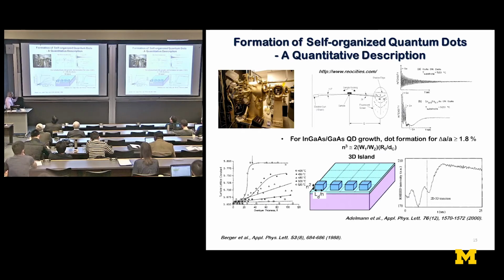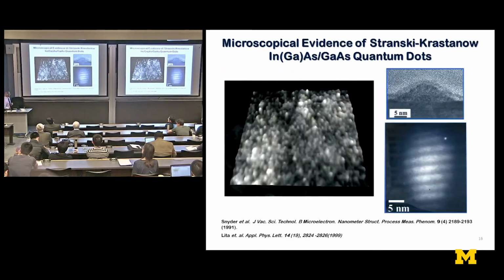And with that, we predicted that for a mismatch greater than 1.8%, and it's now known as the 1.8% or 2% rule, you will have the formation of islands. And we were glad to see after many, many years when people started working on nitride semiconductors, that the 2% rule was borne out here also. When you grow indium gallium nitride on gallium nitride for 18% indium or higher, you get this 2D to 3D growth transition. So this put the whole business of quantum dot growth on a mathematical footing, at least we understood it quantitatively also, and we knew how to grow and design these things.